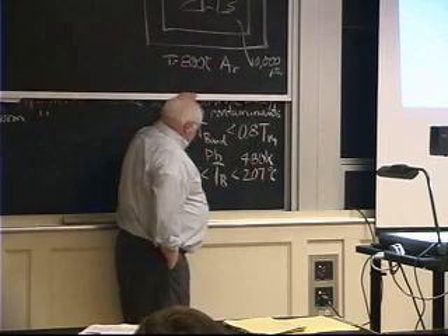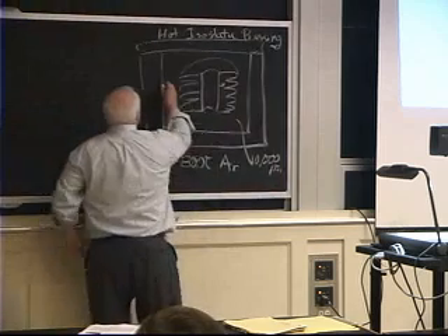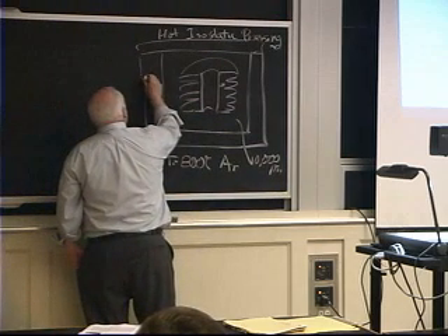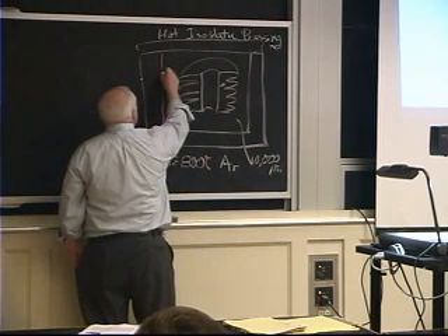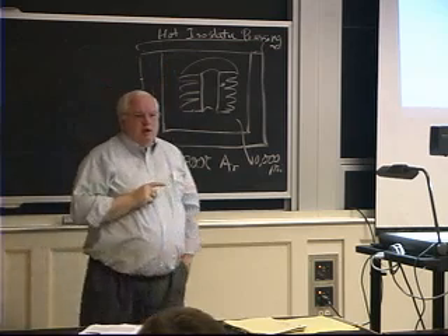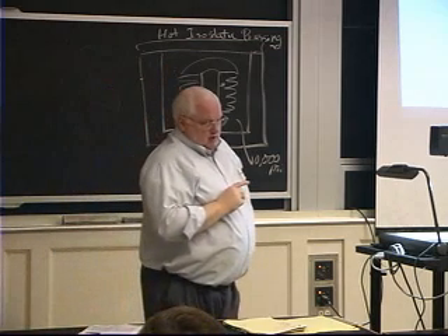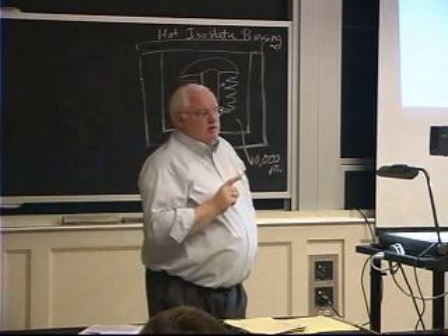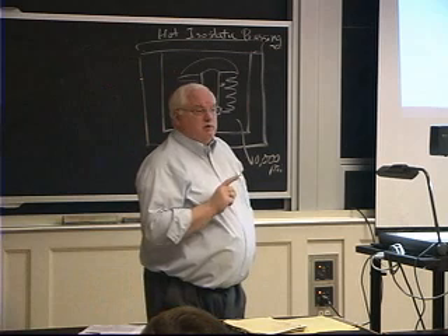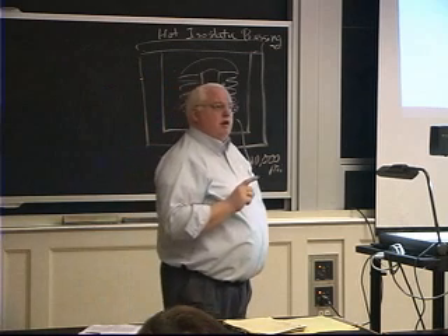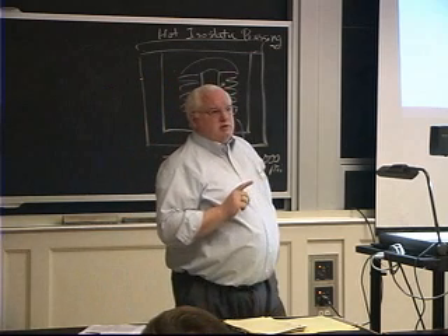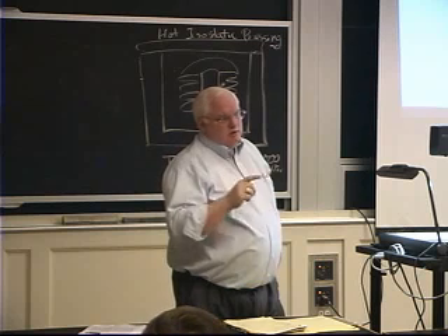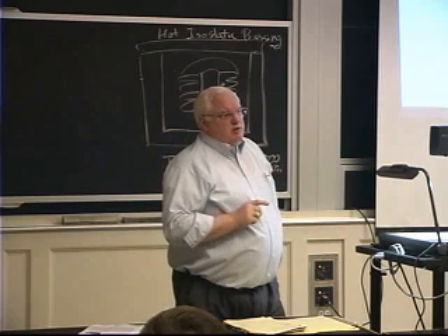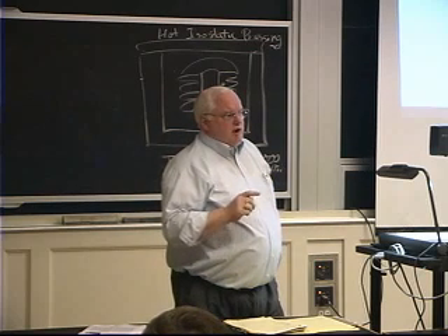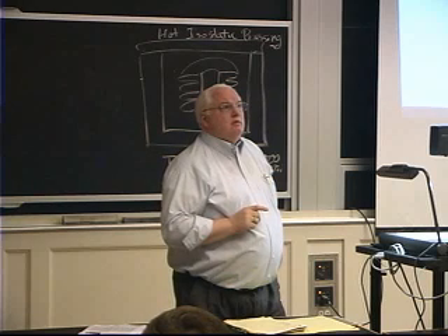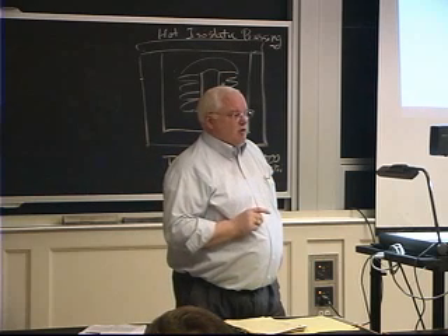Well, it turns out they had a little notch on the outside here. They've done all their stress analysis. This is the world's largest, and in fact, it blew up in the middle of the night. It was about 300 tons, if I remember correctly. It broke up into about 60-some pieces. The average weight of the piece was like 3,000 to 5,000 pounds. It was about 5,000 pounds, if I remember, okay?